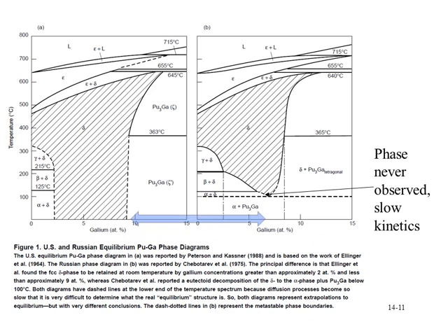The main difference is that the Russians observed a complicated intermetallic, so plutonium alpha phase plus this plutonium-gallium intermetallic, under conditions where the U.S. phase diagram just predicted a single delta phase. Both these phase diagrams are just extrapolations, but they have very different conclusions. And these were important differences where, at the end of the Cold War, they were used as a common research project to understand the behavior of plutonium-gallium alloys under these specific conditions.